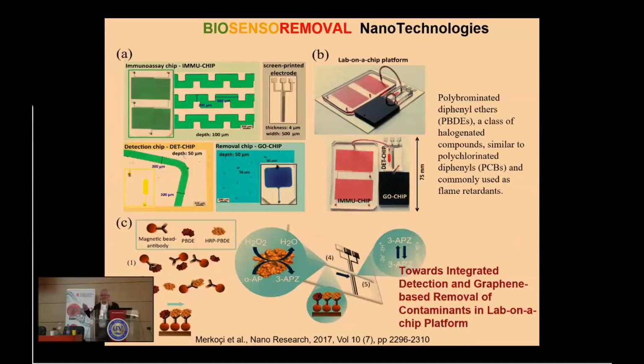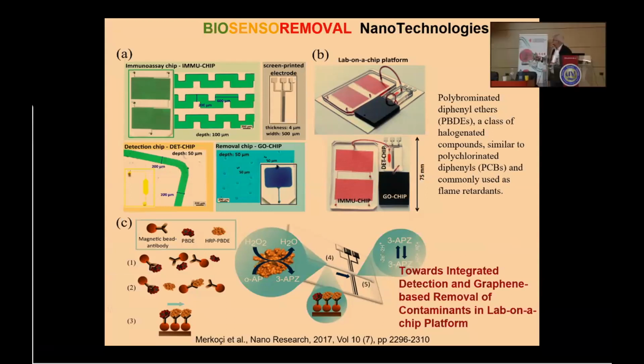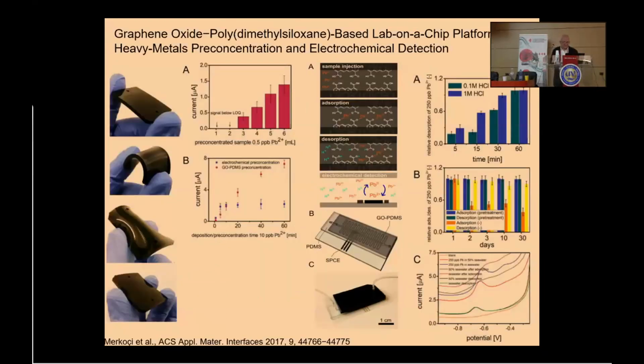Or more about this removal of contaminant, we did by using this GO chip, where you can see this again, but this is very small. It's a graphene oxide modified chip. The electrodes are here. We do the detection of immuno detection, in fact, using some affinities. And afterward, we are able to detect this. In fact, this is a very contaminated, very toxic compound, polychlorinated biphenyl PCBs that are recommended to be detected. So this is also very interesting.